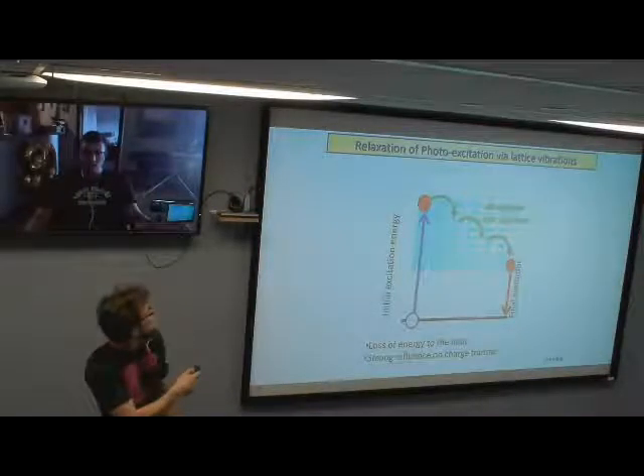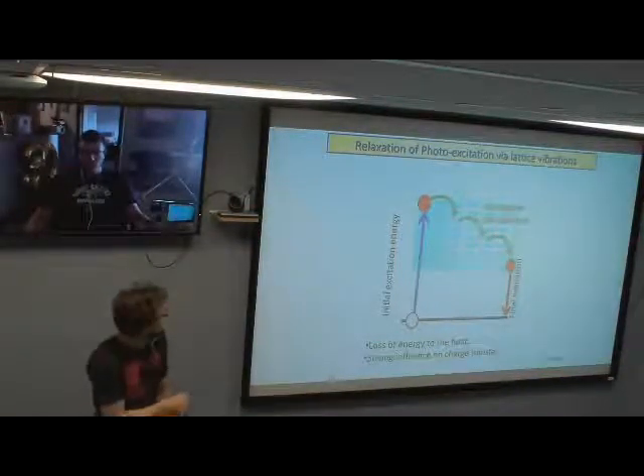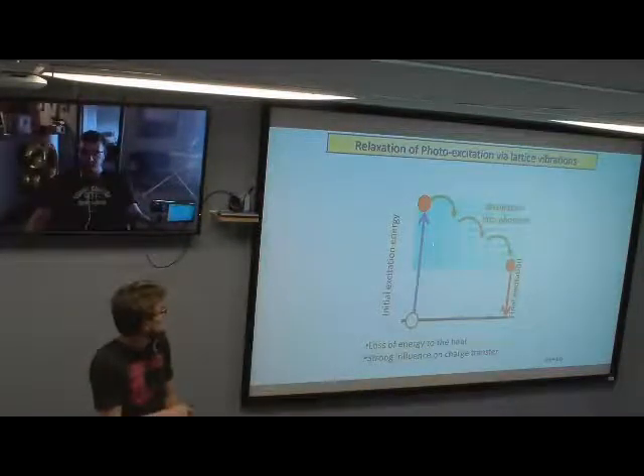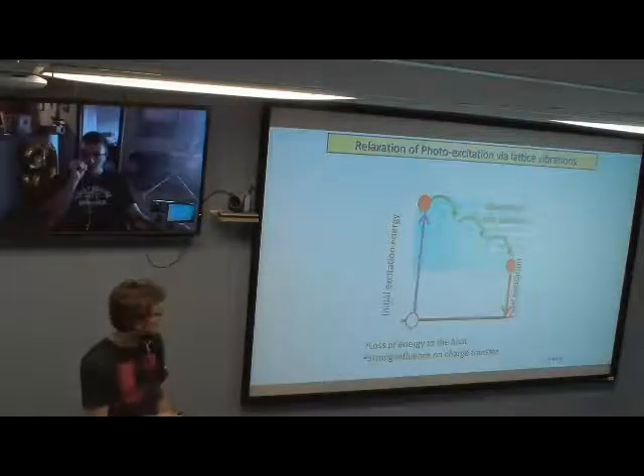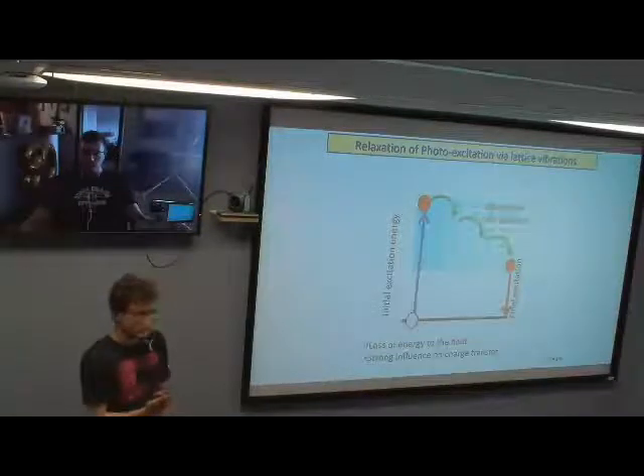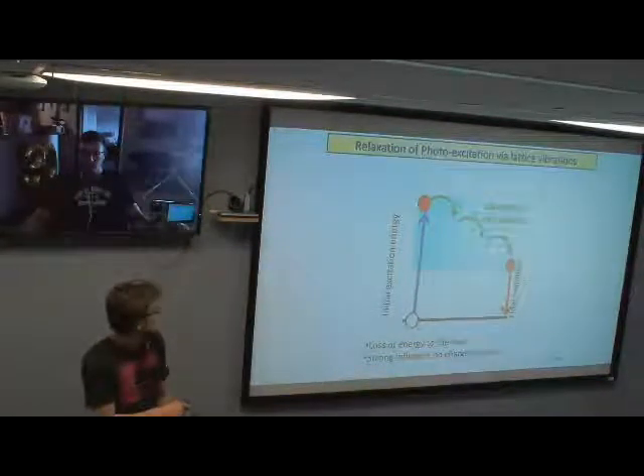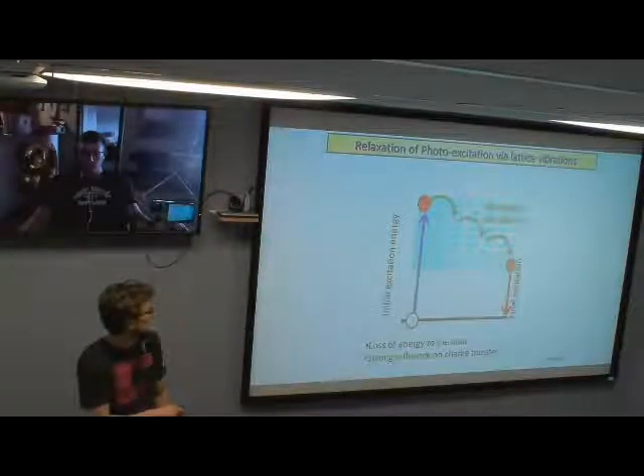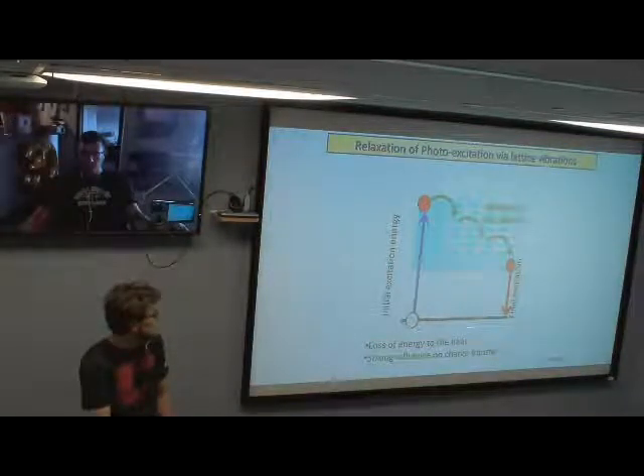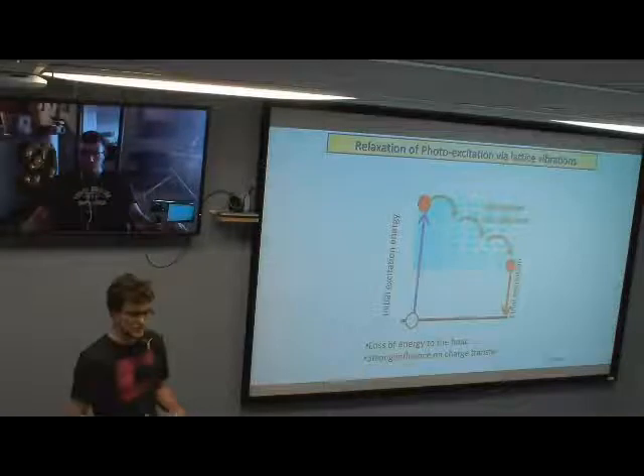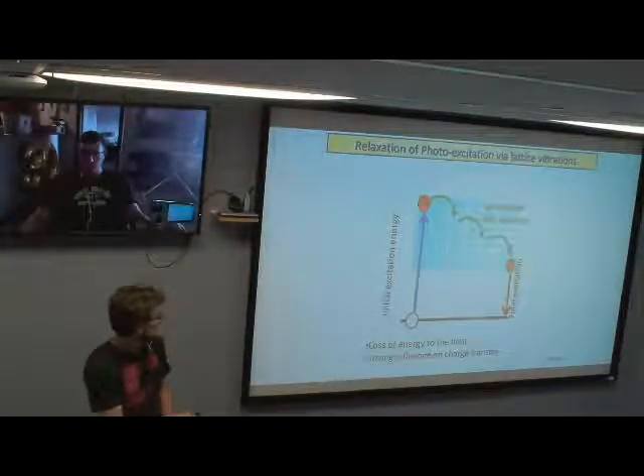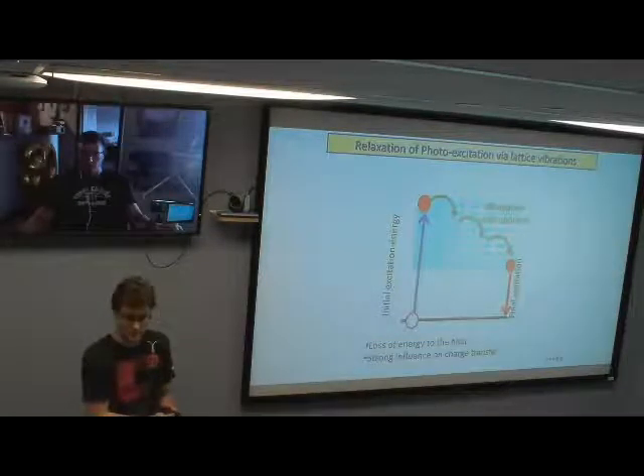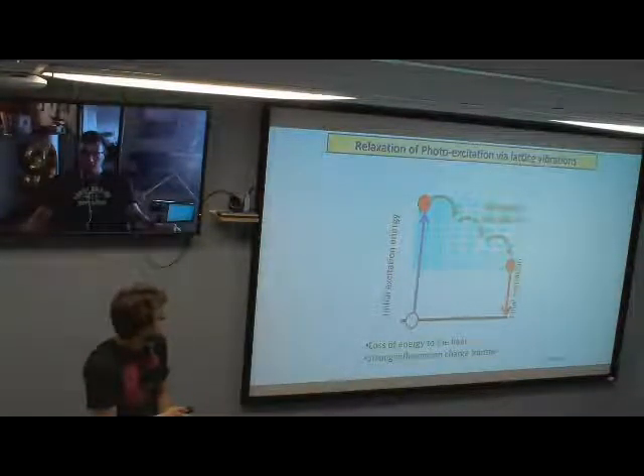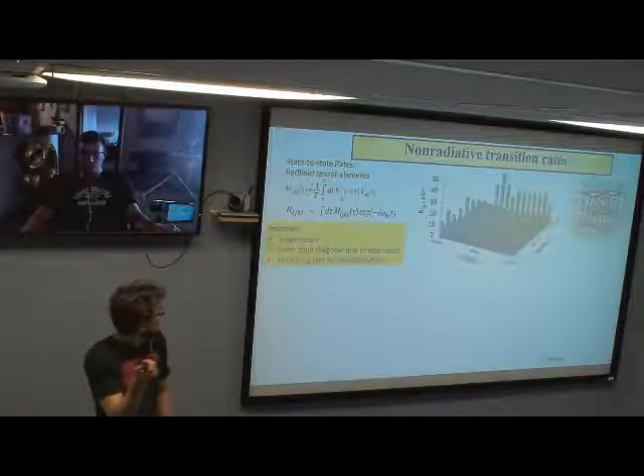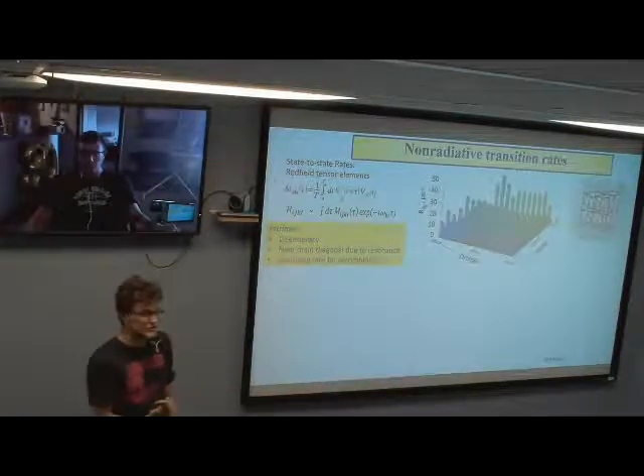And you can probably tell from this characteristic headline, this isn't my slide either, but it has the same information that I wanted to describe. So basically one thing we're trying to model is hot carrier cooling in the system. This would represent an optical absorption transition from some valence band state to the conduction band. And these little blue lines represent possible states in the conduction band. And this is going in time. So in time, this jumps down due to coupling with the phonon interactions, dissipating energy. So it eventually transitions to the band edge, and you can recombine either radiatively or non-radiatively.